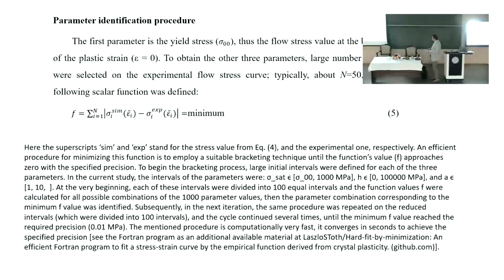The minimization is actually not too complex. You don't need a very fancy code, but there exist Fortran codes which can minimize a function. But what I was doing is simply, we have 3 parameters: sigma sat, H, and A. And I initially just take an interval, the value of sigma sat. Well, perhaps we don't see it in the curve because the experiment is not reaching the saturation stress, so it remains a parameter. But we know it is limited.